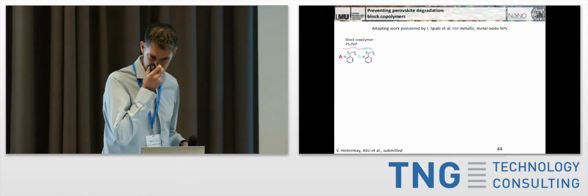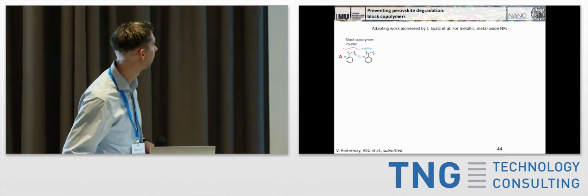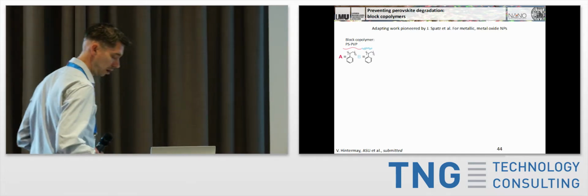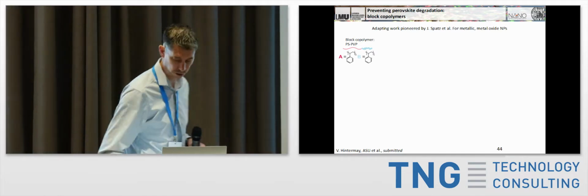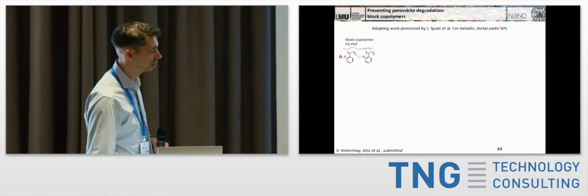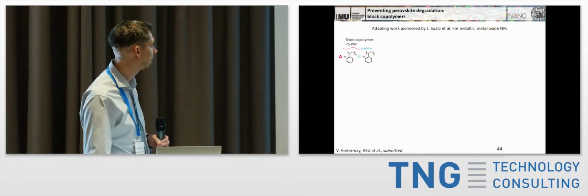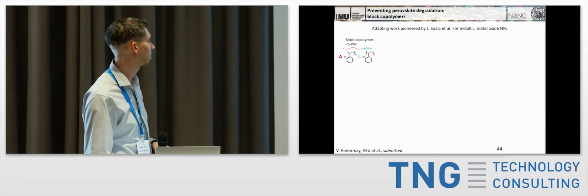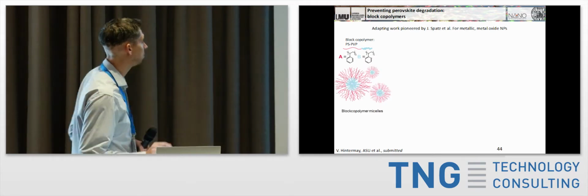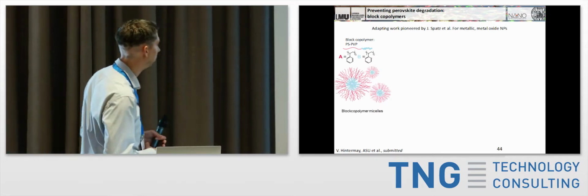This is something that I'm really excited about, that we've been starting up now with our new group, essentially to look into the passivation of these perovskites. And so now we start up with a new synthesis method, but instead of adding organic ligands to the solution to passivate the crystals as they grow, what we're doing is preforming block polymer micelles.